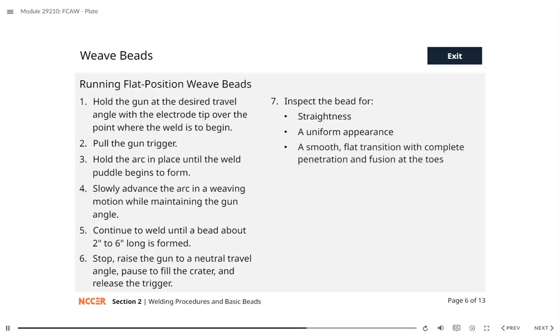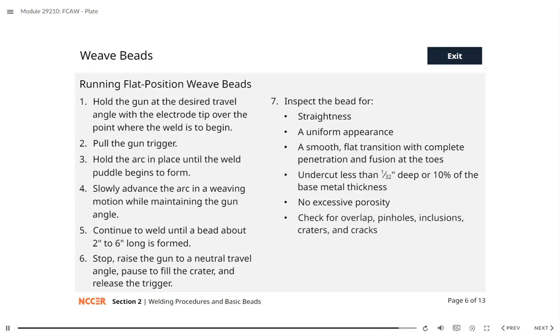with complete penetration and fusion at the toes, and undercut less than 1/32 of an inch deep or 10% of the base metal thickness. Check for excessive porosity. Pores should be no larger than 3/32 of an inch or 2.38 millimeters. Finally, ensure that there is no overlap, pinholes, inclusions, craters, or cracks.